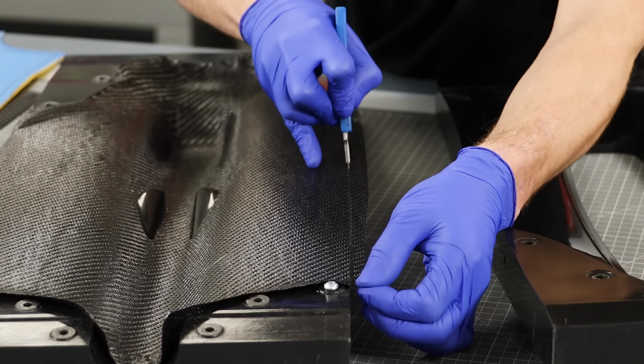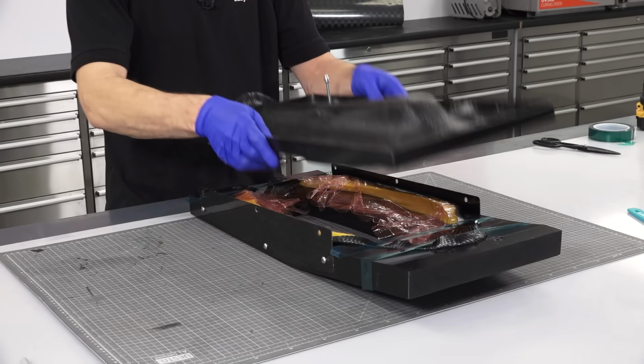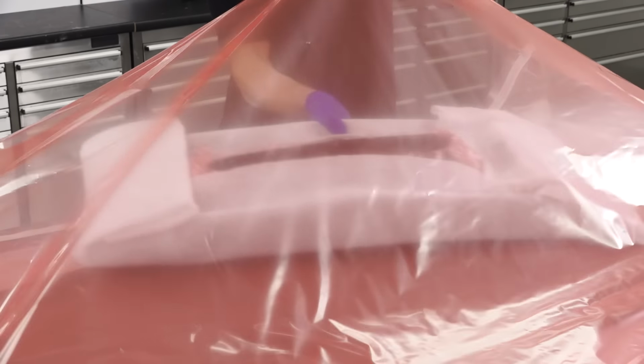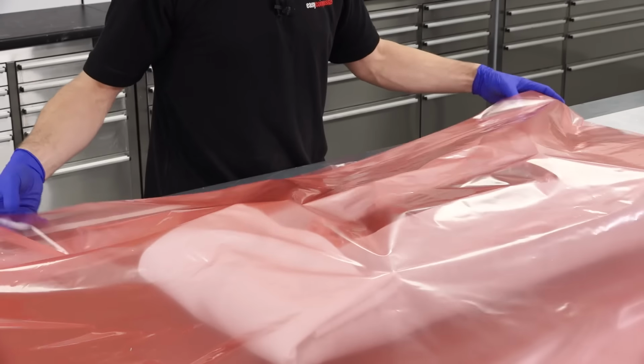Now let's talk about the lap joints. I'm going to be laminating this part in 2 separate halves and then bringing these halves together and vacuum bagging them and curing them into one monolithic structure. But if I was to just laminate each half of this with my 2 plies and finish at the parting line, I would have a very weak structure as the skins would be effectively just butt joined with no fibre reinforcement crossing over that seam.